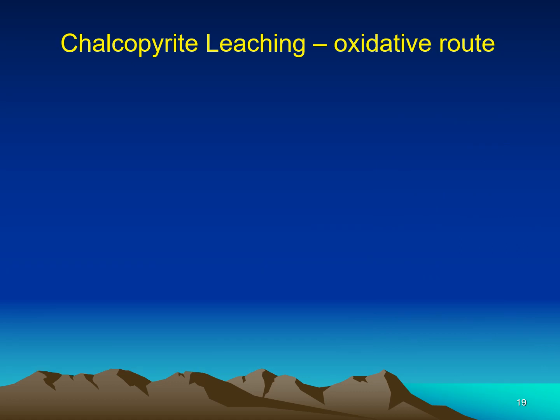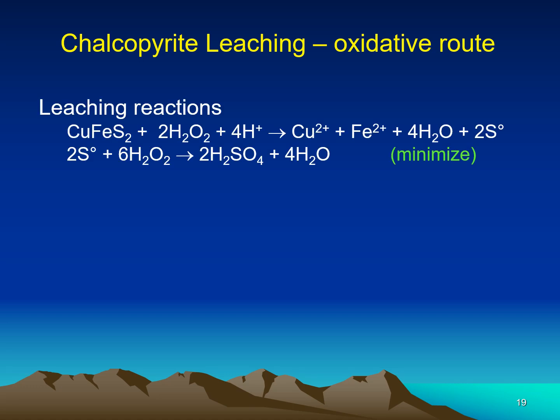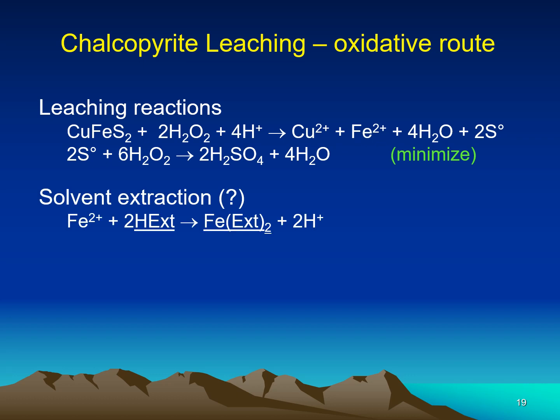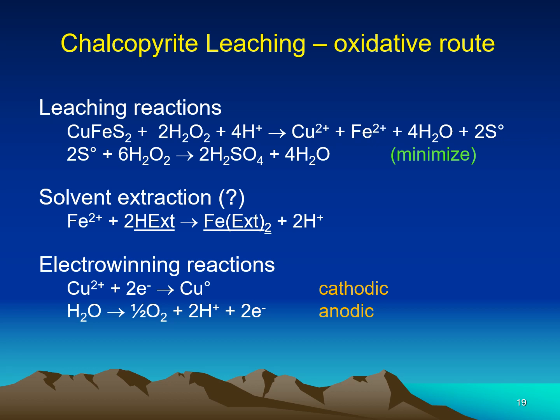In our group, we have also investigated chalcopyrite leaching via the oxidative route using hydrogen peroxide as the clean oxidant. In this case, we form cupric ion, ferrous ion, and elemental sulfur, which in the presence of excess hydrogen peroxide forms sulfuric acid. We would like to minimize this second reaction. We can remove the ferrous ion with solvent extraction and electrowin the copper as usual.